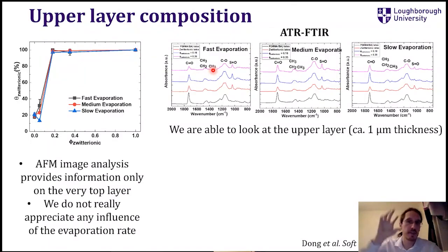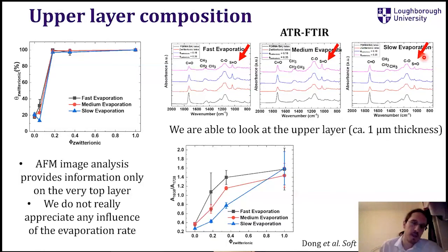And with this, we are looking at the first micron of the coating. And then we are just basically following one of the functional groups, which is related to our functional particles. And then we can see how much there is depending on the amount of functional particles and depending on the evaporation rate. So we'll basically get this graph where what we are seeing is that the amount of functional particles on that first micron layer is optimized when you're evaporating faster. In this case, it looks like you are trapping more particles at that first layer. So we always have a high amount, but it looks like evaporating faster seems to be better.